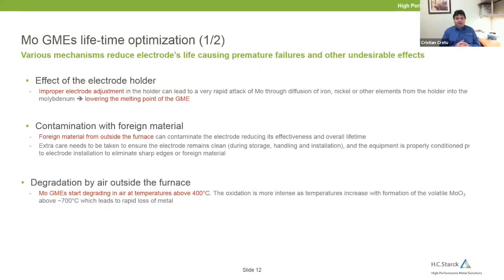Contamination with foreign material. It's similar. If contamination comes not from the holder, it could come from other areas, from outside. So when installing and using, extra care needs to be taken that the electrode remains clean and the equipment is properly cleaned and controlled, so that any foreign contamination or edges or sharp corners that could scratch or damage the electrode or contaminate the electrode are eliminated.